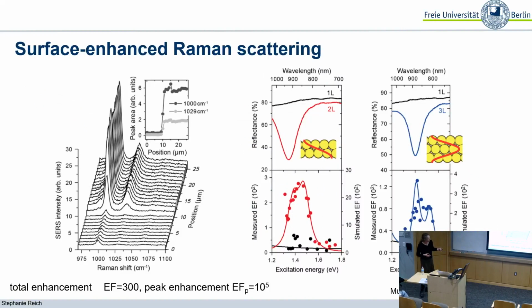And here is a scan where we start from a single layer of these gold nanoparticle supercrystals, where we cannot excite this hotspot, we cannot couple to the far field. And then we go to a bilayer, and all of a sudden we have the excitation of these polaritons. We get the very strong hotspots inside, and you can see very nicely how the Raman intensity increases. But then if we keep going, the Raman intensity really stays the same. And you can scan over large areas of your sample, you can change polarization and so on, and it will not.